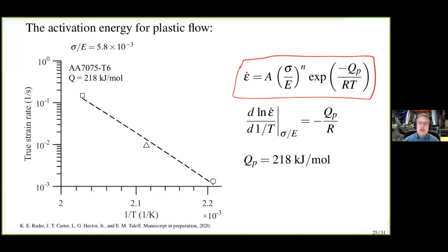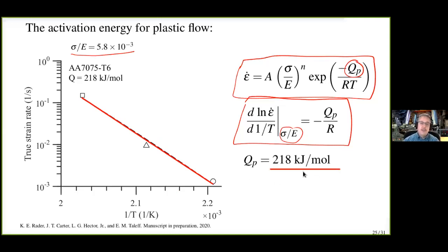So we took this model, and from this model, we have activation energy. In this case, it's an activation energy for plastic flow. By rearranging this equation, we can measure the activation energy if we have data at constant values of sigma over E. So that's exactly what we plot over here on the left-hand side: logarithm of strain rate versus 1 over T in Kelvin. And we see here, at least for the data sets that are available, we get something close to a straight line. That gives us an activation energy for plastic flow.